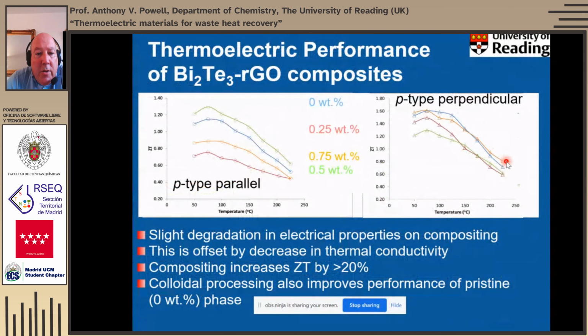And what that does is it increases our figure of merit. Although we get a slight degradation of the electrical properties when we make the composite, that's offset by those quite substantial decreases in thermal conductivity. We end up increasing ZT by about 20%. At our maximum ZTs here, this is the perpendicular orientation, we can get up to about 1.6, for instance. What's also interesting is that we can actually improve the performance even of the pristine phase that doesn't include the carbon. We think that's because by putting it through this colloidal process and the ultrasound, we reduce the grain size quite significantly, and that can contribute to reduced thermal conductivity and consequently higher thermoelectric performance.